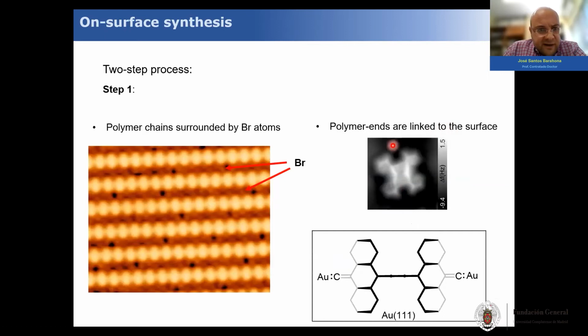You can see here that in between the chains there are small, darker dots. They are atomic bromine in between the chains. And you can see from the color scale that, as I have represented schematically, when you have the dimer, the edges of the molecule that are linked to the gold surface are going down, so they are observed as dark, whereas these other edges, which are on top, are brighter.